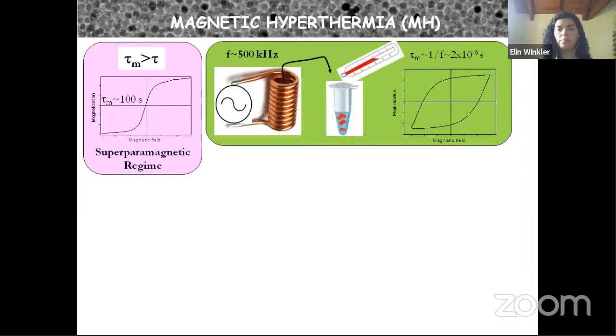So with that idea, we propose to design a material. As we said, we need nanoparticles that behave superparamagnetically at room temperature. That means they do not present remanence, so that the nanoparticles do not agglomerate and can be very well dispersed in a medium. This is the behavior when you perform static measurements, when the characteristic time of the equipment is very large. And when you apply an AC magnetic field, which in hyperthermia has a very large frequency, the characteristic time of the experiment is very, very low.